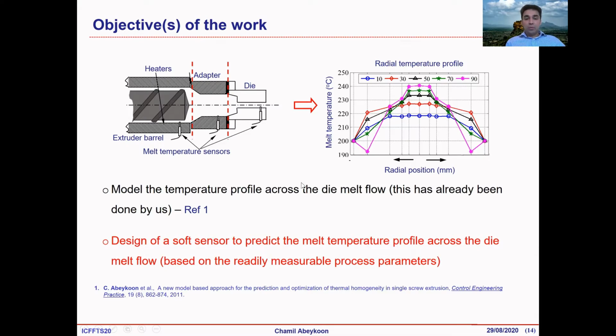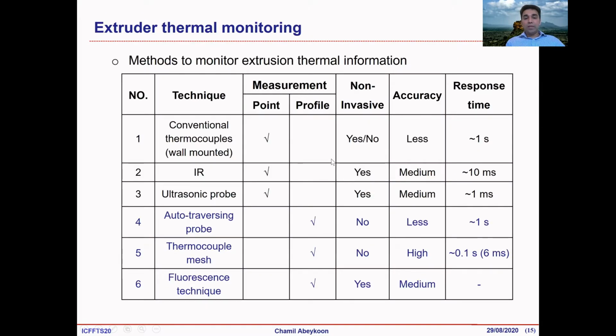So we wanted to develop a model to predict this melt temperature profile, and by having that model, we wanted to develop a soft sensor. That is what our target was in this study. Ideally, if you set 200 degrees here, we need to have 200 degrees across the melt flow cross section, but we can't get that. This is the actual result.